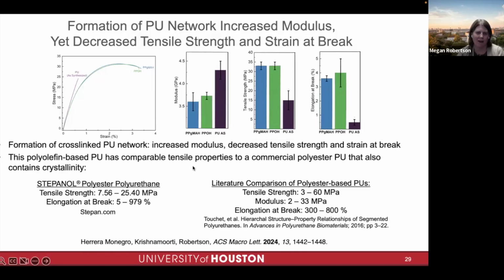If we look at polyester polyurethanes, that could perhaps be a good comparison because polyesters can also crystallize just like polyolefins. So if we look at the tensile strength range, we're in a reasonable range. Modulus, we're quite high, and we're low on elongation at break. So this is making a high modulus polyurethane, which is fairly brittle based on this initial proof of concept. However, I will note that we have not spent any time optimizing this system. I told you all of the molecular parameters we can tune, and there's really a lot left that we can do in order to achieve a variety of properties in this type of material. And so we're really just scratching the surface with these initial experiments.